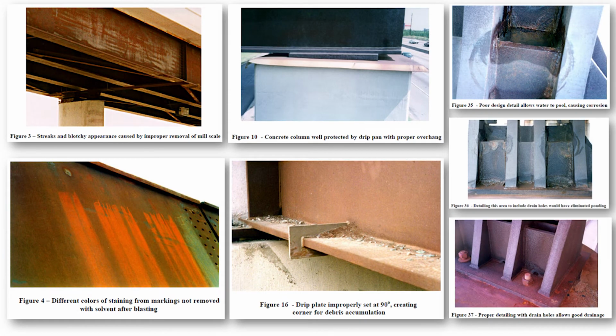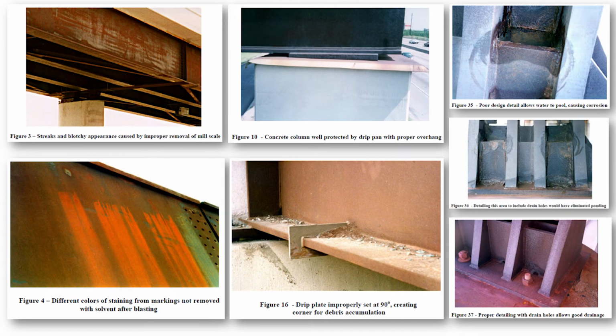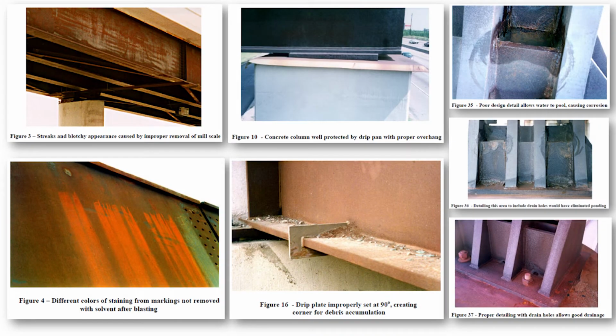Now this bridge on the bottom left is in the shop yet, but if you were to get the steel out there with markings on it, the typical shop marks, then you would be able to see those. And in the picture in the middle, you see a drip plate, also called a drip bar. Those are very good for diverting water away from piers to help control staining, but they're supposed to be at an angle. So we saw some cases where they were square, and if they're square, they'll trap debris and moisture and be a durability problem.